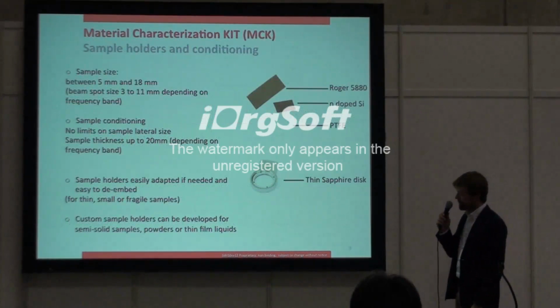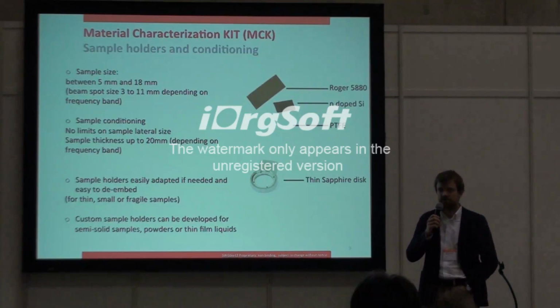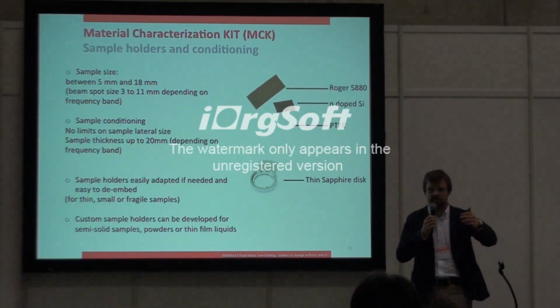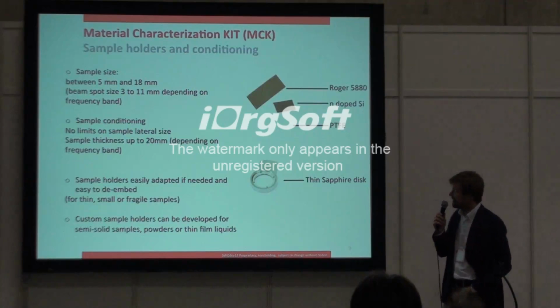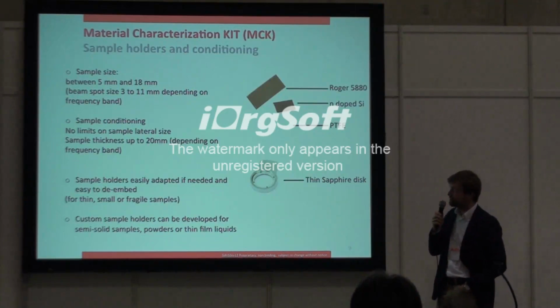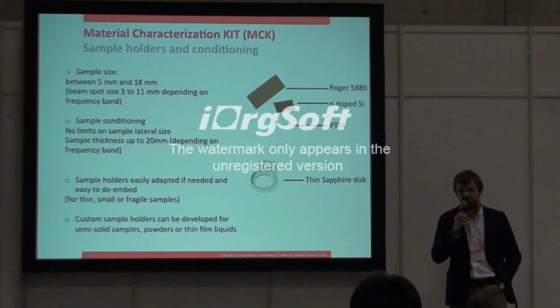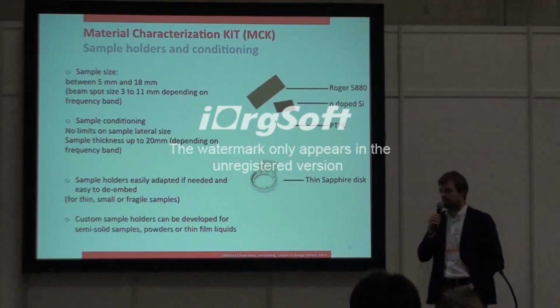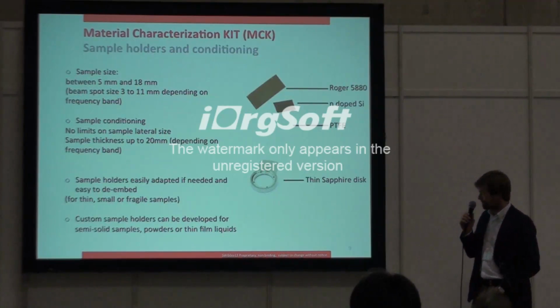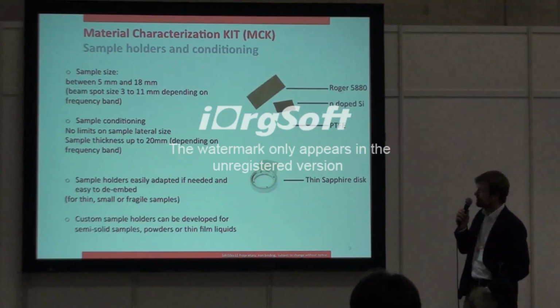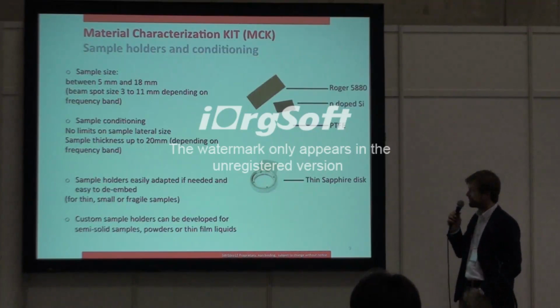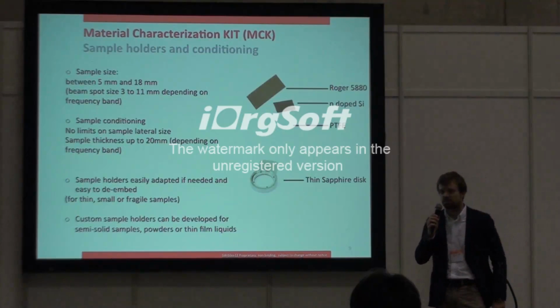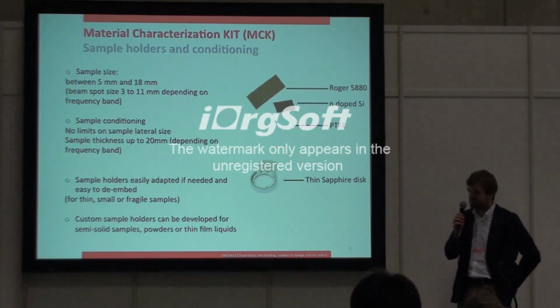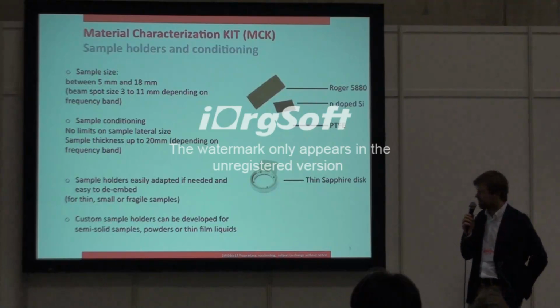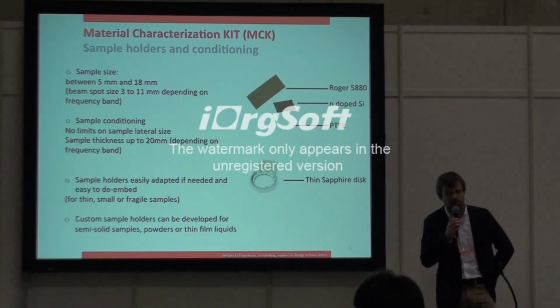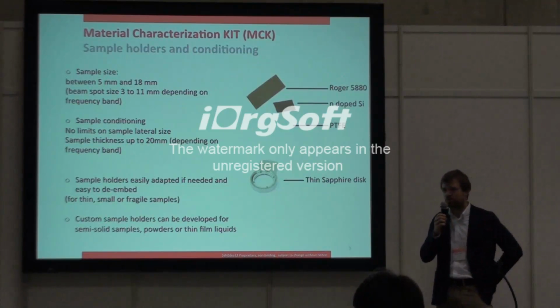The aim of the device is not to require any sample preparation, so there's no limitation on the lateral size of the sample that can be inserted into the device. The thicknesses of the samples vary from 5 millimeters to about 18 millimeters, depending on the frequency at which we operate. So the higher frequency we go, the thinner the samples have to be. The spot size under investigation is on the order of 3 to 11 millimeters, again, depending on the frequency at which you operate. And for some applications, it's of interest to build sample holders, for instance, to hold very fragile, very thin samples. So we do supply sample holders for those. And we are also in the process of developing custom sample holders for more complicated samples like powders, foams, or liquids.